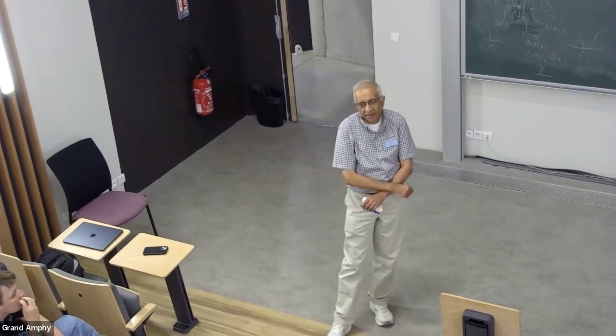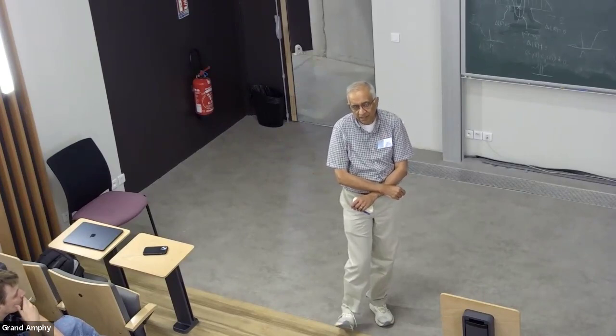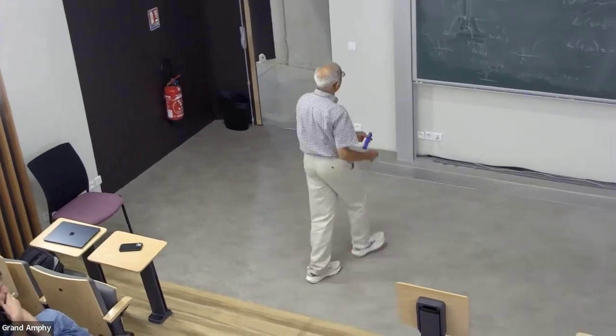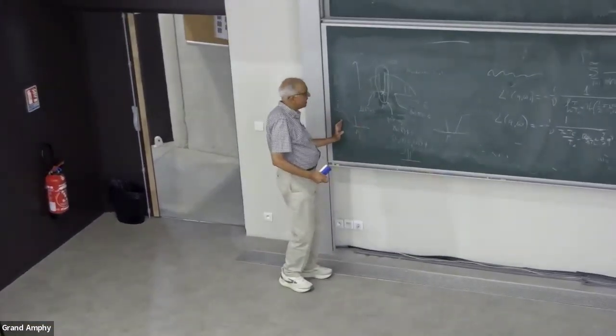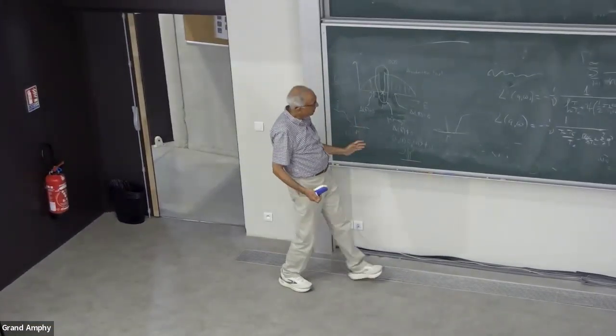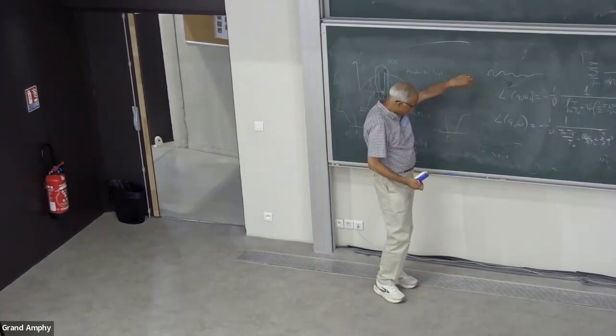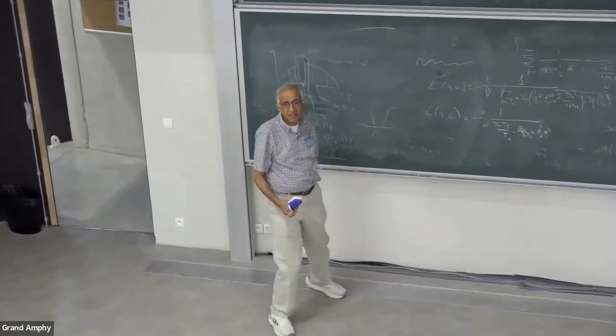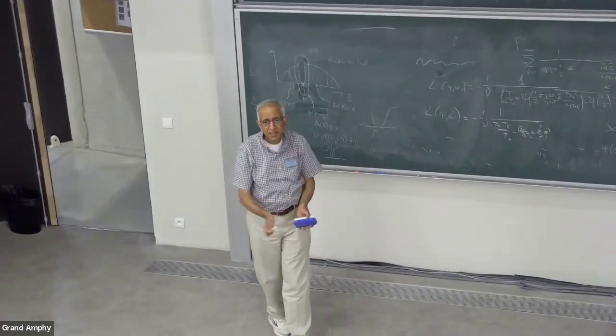Those states that are far away will be hugely localized, and most likely we never get a real tunneling. You can, but you have to give a large bias on the negative side. You can pull stuff out. Here you give a large bias on the positive side, you can put stuff in. Because that's what tunneling density of states is.